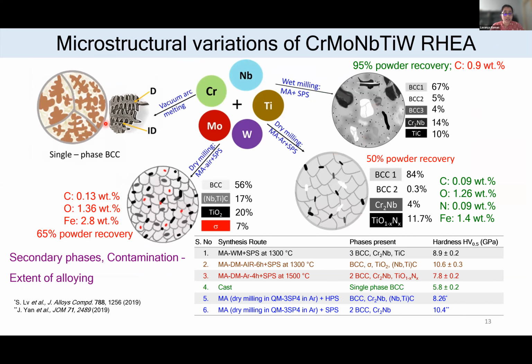So now to summarize the phase formation and the microstructural variation of this composition when we make it through different routes. We can see that the casting route gives a single phase BCC, whereas the powder metallurgy route, depending on either wet milling or dry milling, and also the milling atmosphere and the media, gives different secondary phases. So one thing we learn is that the extent of alloying in the powder metallurgy route decides your secondary phase, and the milling atmosphere and the milling media also help you identify what secondary phase you can have.